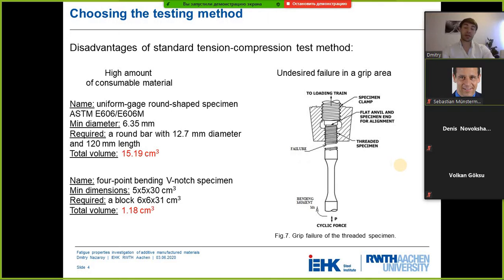In this work, as is normal for lab investigations, I tackled a problem, and the problem is the lack of material. In this circumstance, I had to analyze and choose the most appropriate method of testing fatigue properties. The most popular is the tension compression test. In order to produce a tension compression specimen with the smallest diameter, around 15 cubic centimeters of the material is required, which is much more, for example, in comparison to the proposed small specimens.